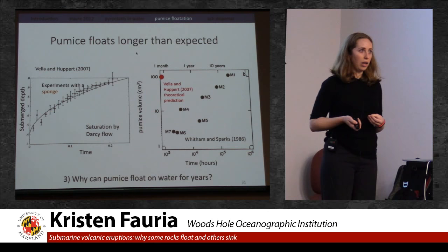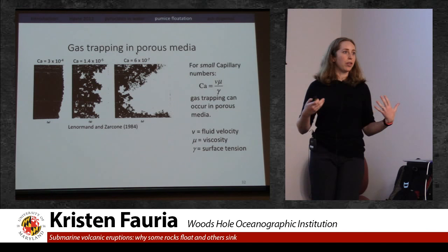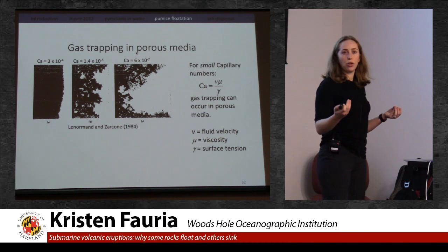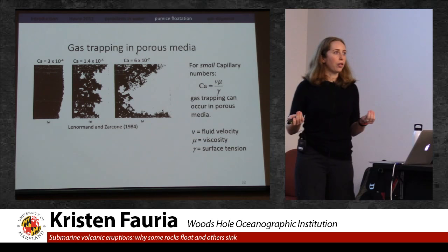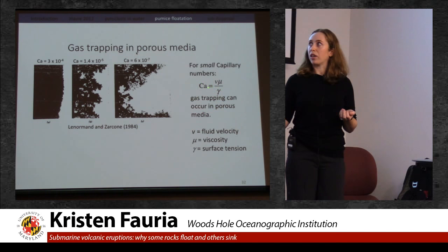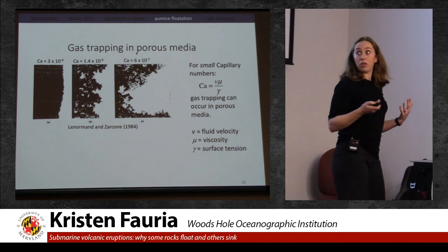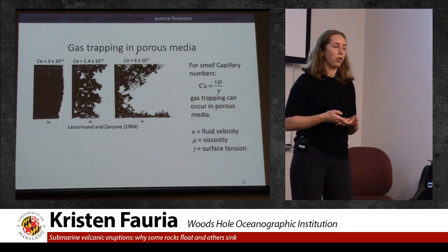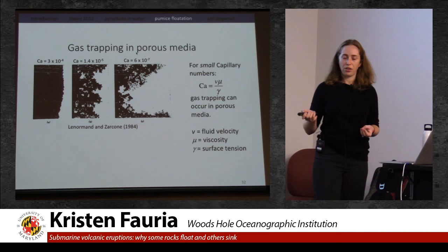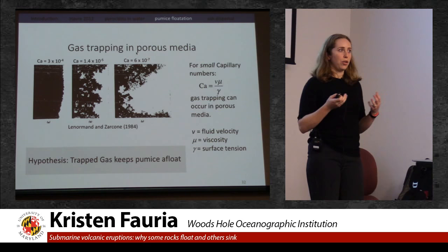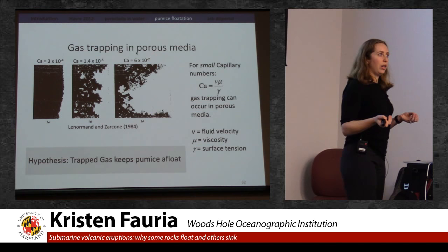However, there are circumstances when water infiltrates a porous media that the gas can become trapped. And by gas, I mean air or CO2 or a non-condensable gas phase. The propensity for gas trapping increases as the effects of surface tension increase, so as the capillary number, the ratio of viscous to surface tension forces, goes down. This gas trapping process is really important for oil reservoirs and for CO2 sequestration. It's been studied in a number of other hydrologic contexts. So my hypothesis is that it's the trapped gas, the ability to surround liquid water around a non-condensable gas like air or CO2, that allows pumice to stay afloat in rafts for as long as they do.